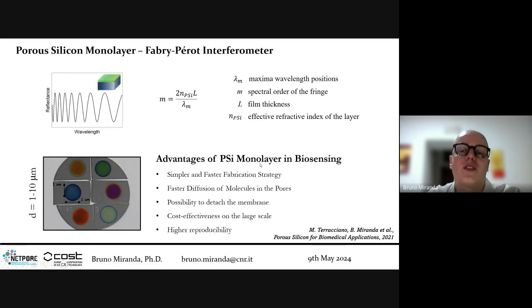The advantage of monolayers in biosensing is that we have a simple and fast fabrication strategy. The molecules for biosensing purposes diffuse faster in a monolayer rather than in 20 layers of porous silicon. This makes the time fast for the interactions and for the calibration curve construction, and also allows the possibility to detach the membrane for the creation of nanoparticles with photoluminescence properties.